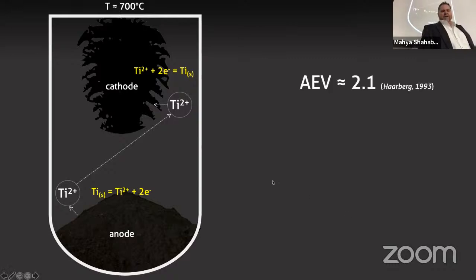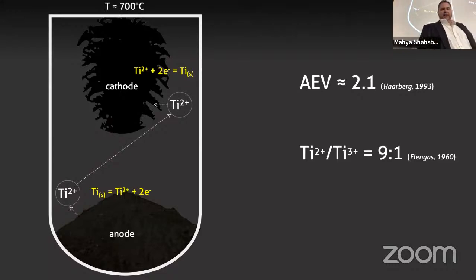That is the great way for the process to work. The reality is that the average oxidation state of the titanium in these molten chloride melts is not 2. It's above 2. That is because there's a ratio between TiCl2 and TiCl3 anytime you have titanium metal in that same system. The thermodynamic equilibrium between them is such that you mostly have the 2+, but you get some of the 3+. And you're like, okay, fine, you've got some of these pieces along. Why is that an issue?